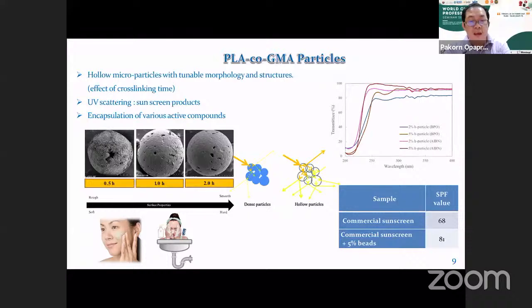Also, we can vary the morphology of these particles. By making them have a rough surface like this, or become smoother and smoother here, we can control this morphology by varying the degree of cross-linking of the double bond that we have in the copolymer chain. So with lower degree of cross-linking, the copolymer chain has higher degree of movement, and they can form crystal. And as a result, this crystal structure shows up as a rough surface in the particles.